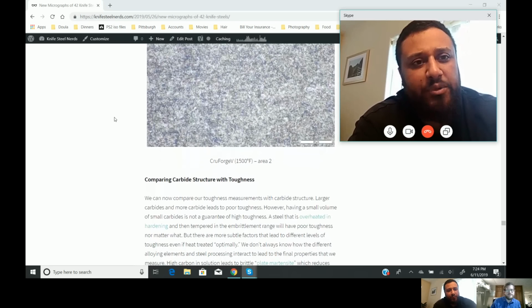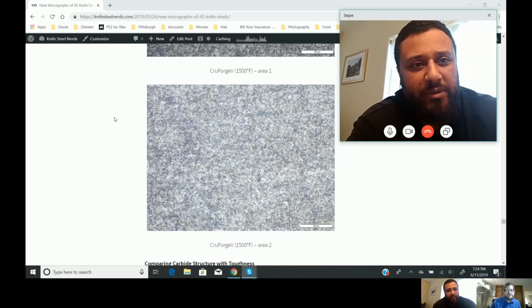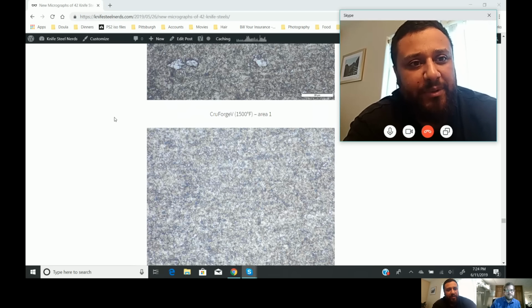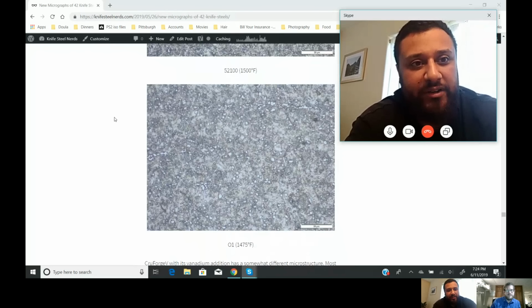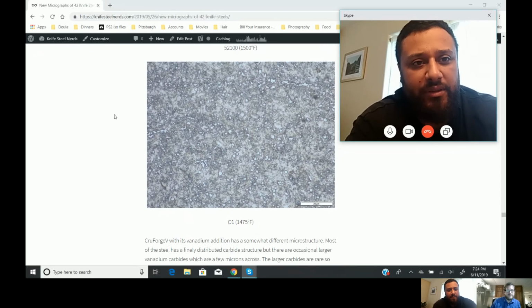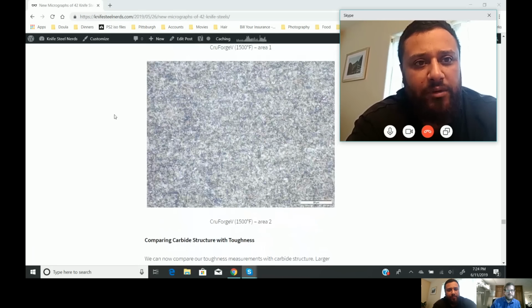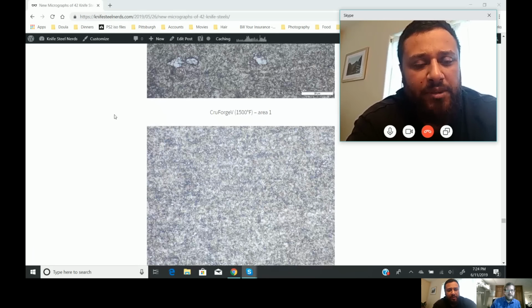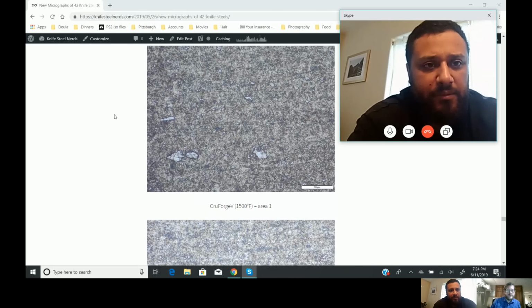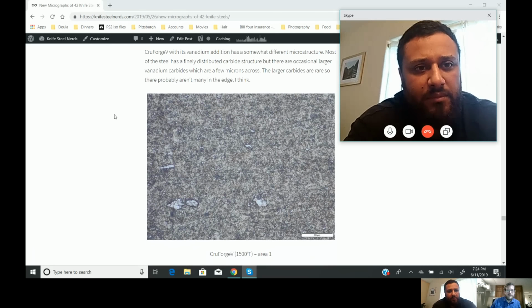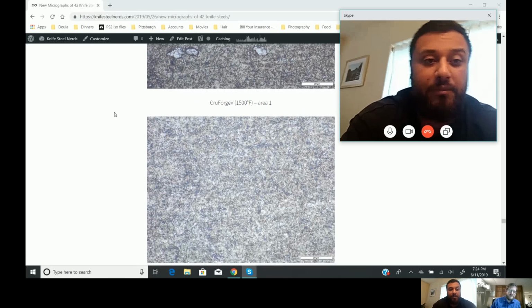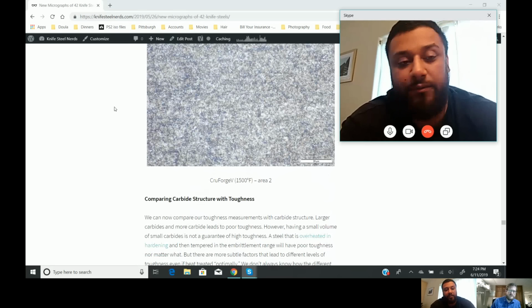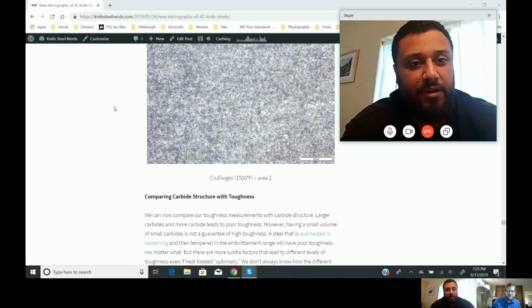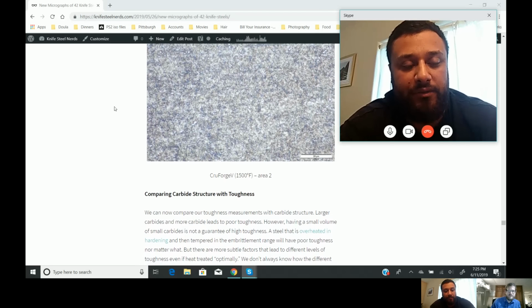I mean, if we look at this beautiful picture of it compared to the 01, the vanadium seems to promote a finer carbide. If we look at that one snapshot area versus the 01, even finer than the chromium of the 52100. Yeah, I think Cruforge V looks like a decent option if you want a little bit of wear resistance in a forging steel. Tested really good for not being a PM steel. I mean, so far that's the most wear resistant carbon steel I've come across.